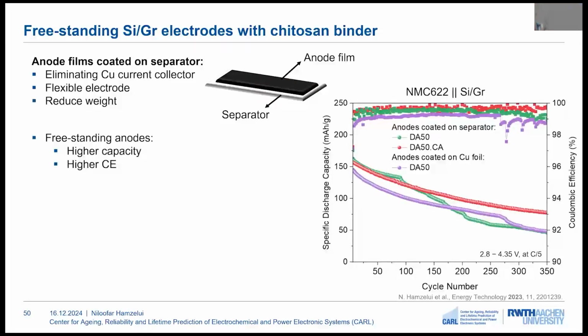And here we can see the electrochemical performance of the electrodes against NMC 622 cathode, using freestanding electrodes and the electrode coated on top of a current collector. In the case of the freestanding electrodes, I have also used the pure DA50 chitosan and the cross-linked binder. It can be observed that both of the freestanding electrodes showed higher capacity and better performance compared to the electrode which is coated on copper foil.